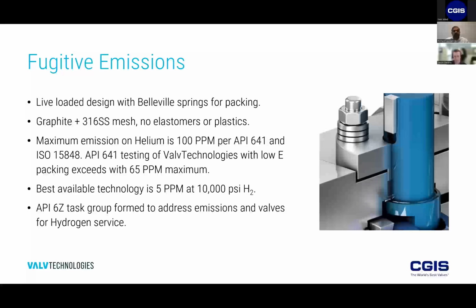But as I mentioned in one of the earlier questions, there is packing that has been specifically developed for hydrogen service, but it's not truly zero leakage. It's about 5 parts per million worth of leakage. And that's actually at 10,000 psi of hydrogen, which is a fair reflection of how these systems are likely to operate under high pressure.